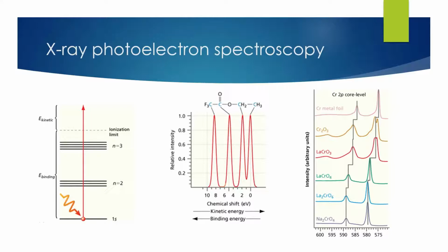Now, the most practical use of this is to detect oxidation on metal surfaces. So here we can see a scale of different chromium, so pure chromium, and then different oxidation levels. Again, there's more electron withdrawing groups on this chromium down here than there are up here. And you can see that there is a shift. So this gray line here draws our eyes to the various shifts as we go from fully reduced to fully oxidized chromium here.